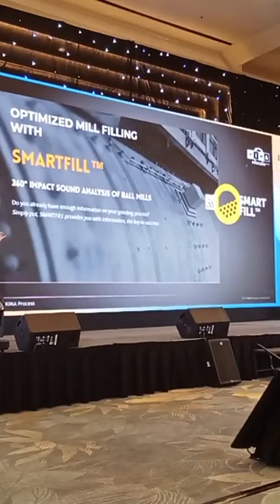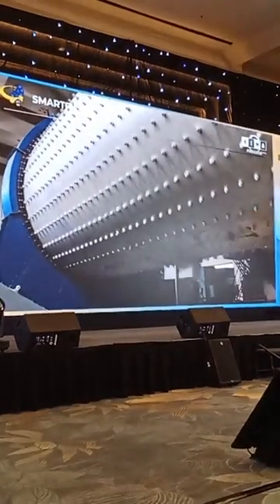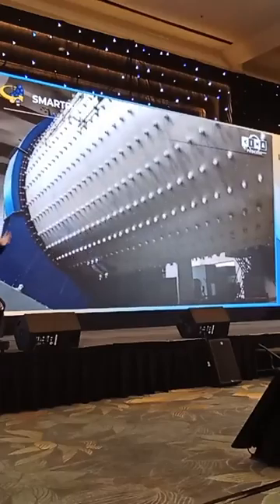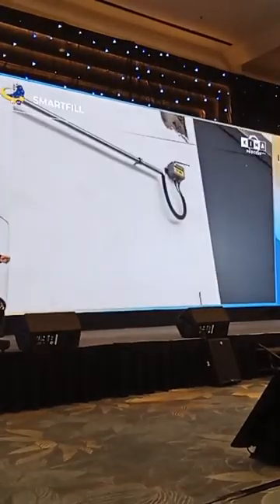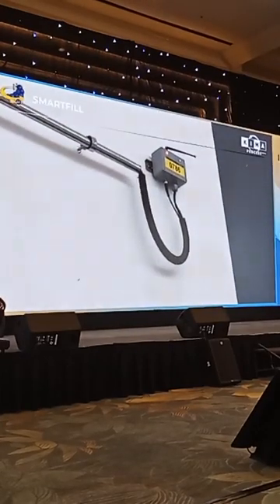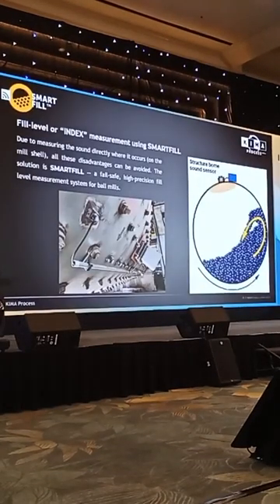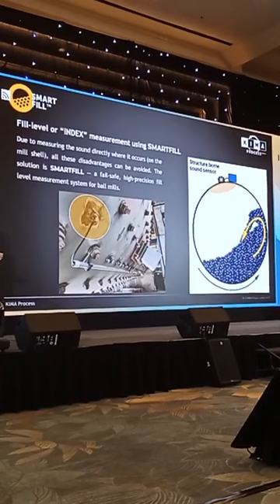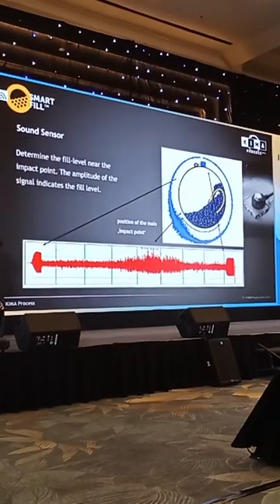We are installed on the mill body itself, and we listen, as you can see in this small video here, with a box on this mill, precisely in chamber 1 and chamber 2 with vibration sensors. And these vibration sensors, which you see here, cover structure-borne sound. So there is no chance for outside acoustic noise to be picked up in this measurement. We are usually 10 to 20 times more precise in measuring the fill level. And the fill level is measured on a 360-degree analysis.